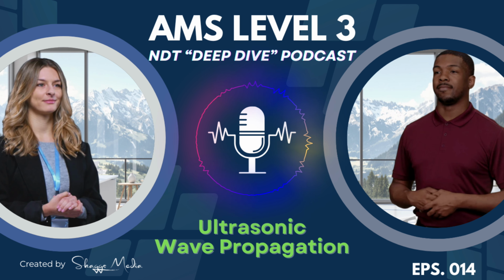If the pulse shape changes, maybe that sharp leading edge you use for your timing measurement gets smeared out or looks different later on. That can really mess with your timing measurements and make it harder to accurately size a flaw just based on how long the sound took to travel. Wow, okay. That really brings the physics down to the shop floor, doesn't it?